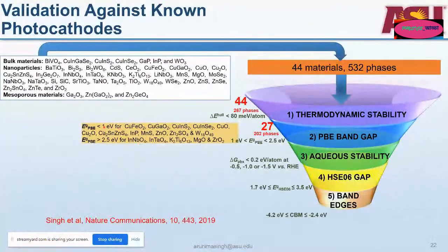And when we look at the band gap, the number of materials which pass through reduced quite a bit. We are left with 27 phases, 27 materials with about 200 phases. And the materials which dropped out had a band gap less than 1 eV, more than 2.5 eV. The ones which had band gap more than 2.5 eV are known wide band gap materials, oxides, and the ones which are less than 1 eV, many of them are known low band gap materials.